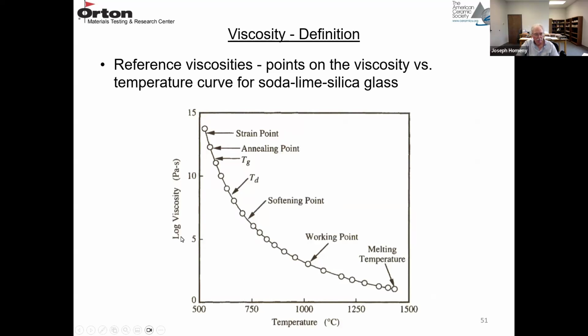And if you plot log viscosity versus temperature, you get a curve that looks like this. The viscosity is decreasing with temperature. This is your melting temperature. Here's your working point. Here's your softening point. Here's the glass transition by the dilatometer method, the glass transition by the fiber elongation or Littleton method, and finally your annealing and strain points.